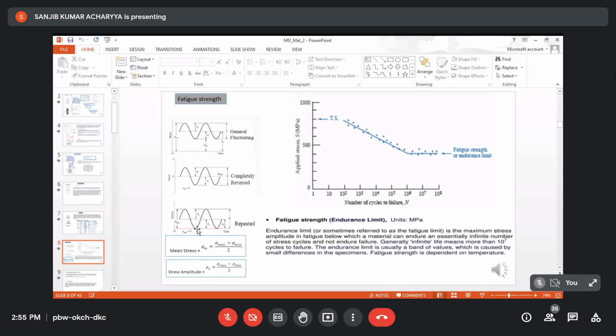Suppose railway axle. It was observed in the 19th century that railway axles, when by calculation, are subjected to very low amplitude of stress and the value of that stress is below the yield point. But it was the general observation that after a certain number of running of the train, the wheels failed, though the applied stress amplitude is far below the yield point. So people tried to inspect why failure occurs. One thing was observed, that on the failure surface, consecutive stretch marks are observed. And by further inspection, it was understood.